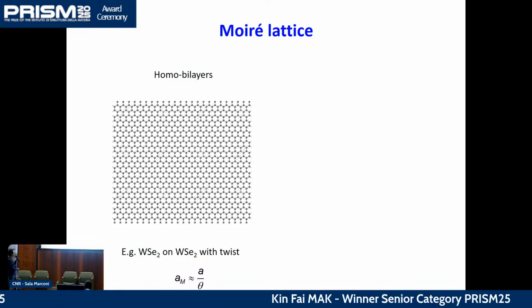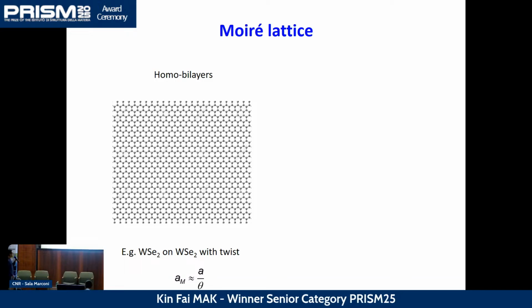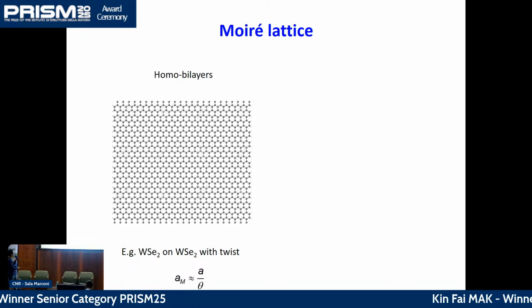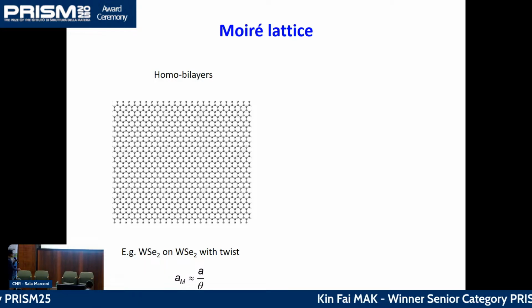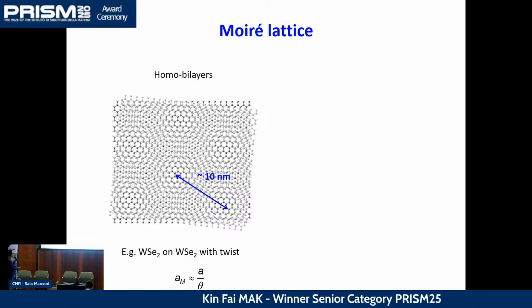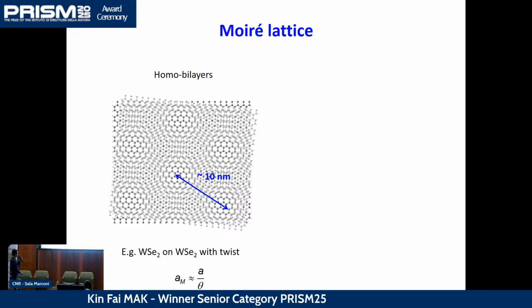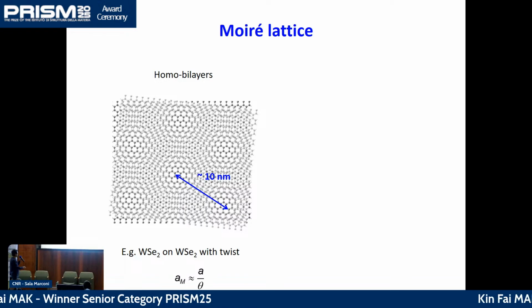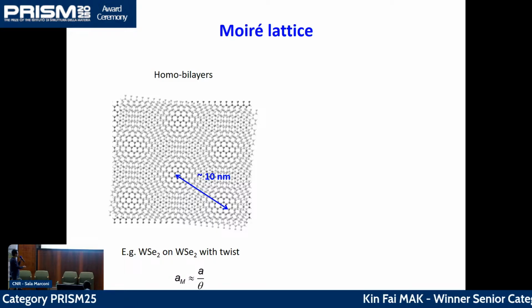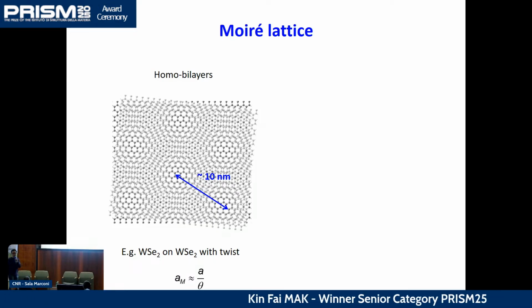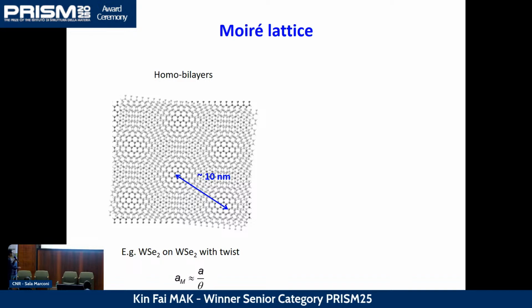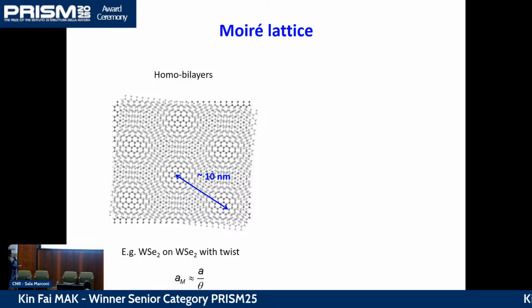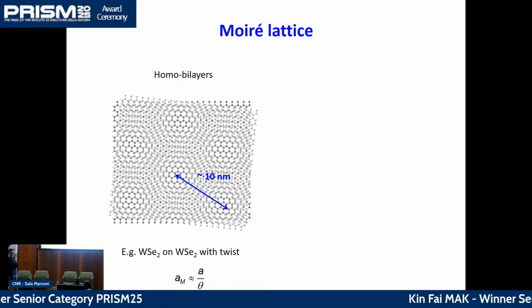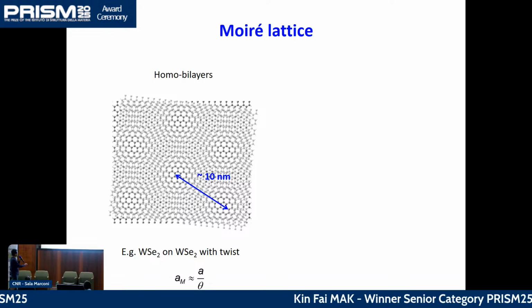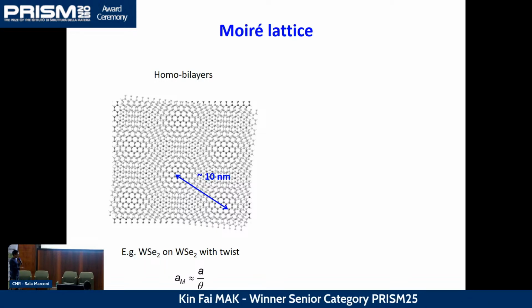Similar to graphene, you can actually create a moire pattern in this material. For instance, you can use two of the same materials, tungsten selenide on tungsten selenide, and give it a twist angle theta like this. Then you can create a moire pattern, a superlattice structure. The period of this lattice, A sub m, is equal to A, the original lattice constant of the material, which is angstrom level, divided by theta, so that you create a period that is much longer than the original lattice constant. We typically deal with a period of about 10 nanometers.